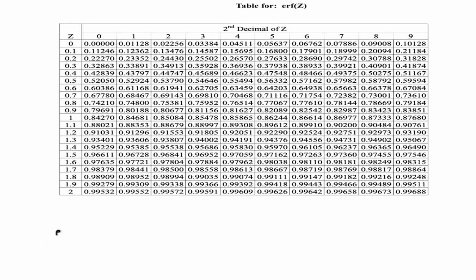Okay. Now, we need to find z such that error function z is equal to 0.64516. Exactly this value may not appear in the table, but we can assume a linear relation within a small range of z. So, let us see one value which comes before 0.64516 and the other which is slightly greater than 0.64516. From this table, we have 0.64203 and 0.64938. This corresponds to 0.605 and 0.606.